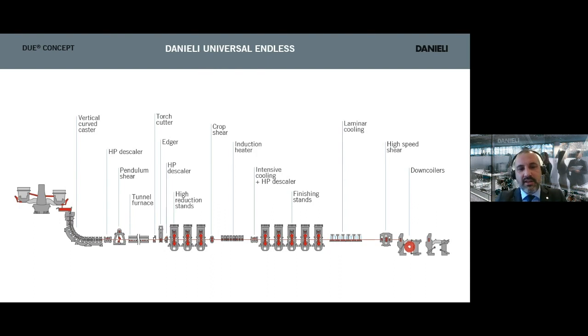130 millimeter slab thickness at mold exit, soft reduced down to 110 millimeter as final slab, followed by a pendulum shear, a short tunnel furnace of about 80 meter length in order to connect the mill area, which is made up of 8 rolling stands separated between high reduction and finishing stands by installing in the transfer bar area a crop shear, an induction heating system, and an intensive cooling system. Of course, laminar cooling, high-speed shear, and the coiler area.